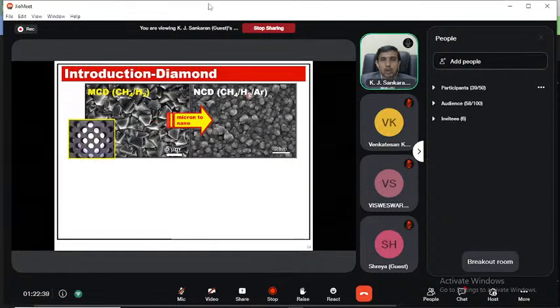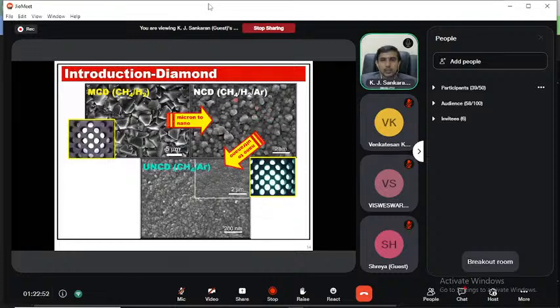And once you add some argon inside this methane hydrogen, it becomes nanocrystalline, with very small grains, nearly around 50 to 100 nanometer. Then what happens if you remove the hydrogen and add only methane and argon? That gives ultra nanocrystalline diamond, which was developed by the Argonne National Lab in the US and patented by them. This methane argon plasma contains C2 and CH radicals, which create ultra nanocrystalline diamond grains, and you can see the bright green color of the UNCD plasma.